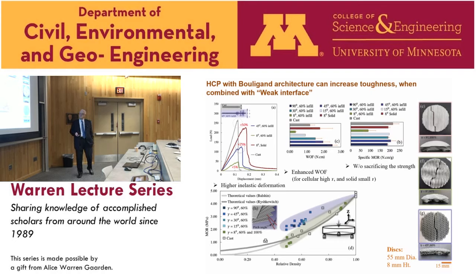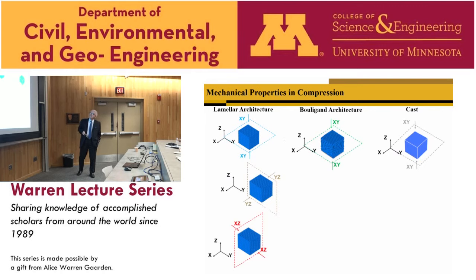Now, when we summarize all of this and look at some theoretical work, prediction of modulus of rupture as a function of the relative density, those are two different models that predicted how the material should perform. And you can see that many of the structures that we created were actually above those lines, which means that we actually achieved higher toughness than predicted in this particular situation. So we outperformed the strength compared to hydrated cement paste counterparts that were solidly cast.